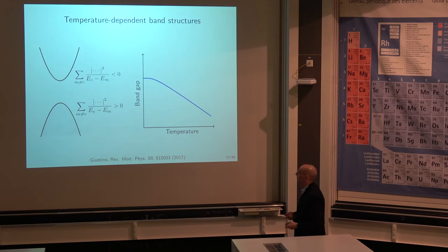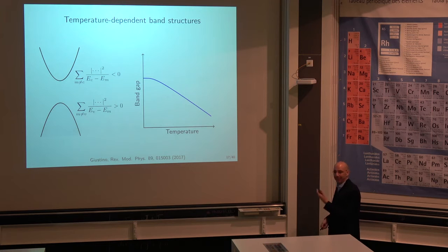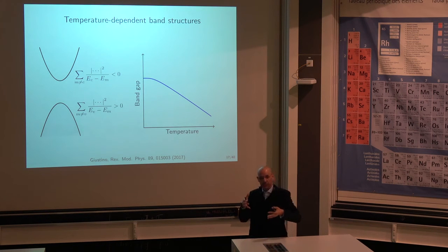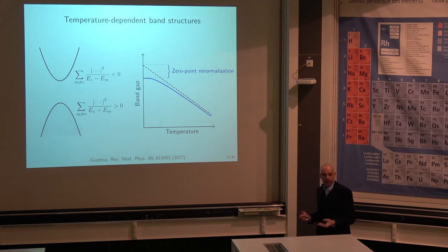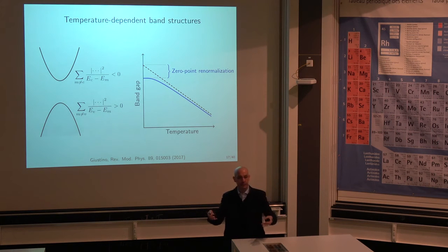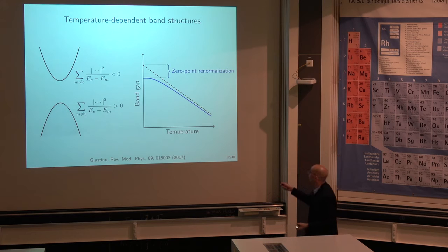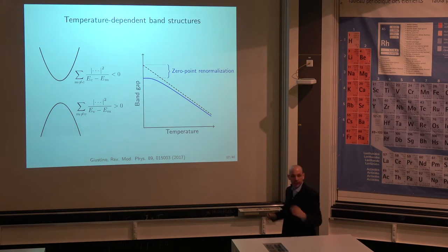If you take the difference, you find that the band gap of a semiconductor in these conditions has this kind of dependence on temperature. Basically, it's flat at a low temperature, let's say, and then it starts becoming linear at higher temperature, okay? And the important observation here is that if you replace this by classical nuclei, so instead of using the mean square displacement from the quantum harmonic oscillator, we just use classical nuclei, we will find a straight line, okay? Precisely because of what I told you two slides ago. So what is interesting in this story is that if you do a DFT calculation at zero temperature, so that's the baseline calculation, you just take a system, relax the coordinates, and then you do the band structure. The band structure will yield the properties at this point, okay? So what the experiment is measuring is this point. So this is not the same thing. And this difference is what we call the quantum zero-point renormalization of band gaps and band structures.